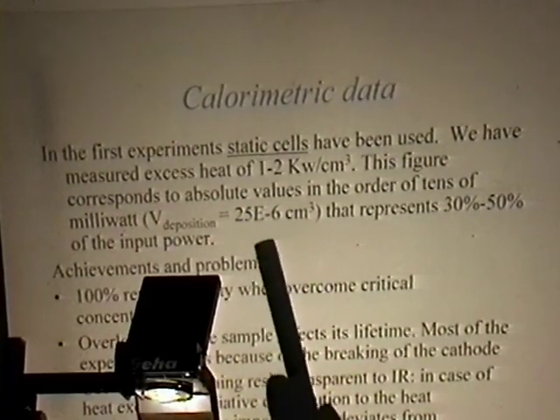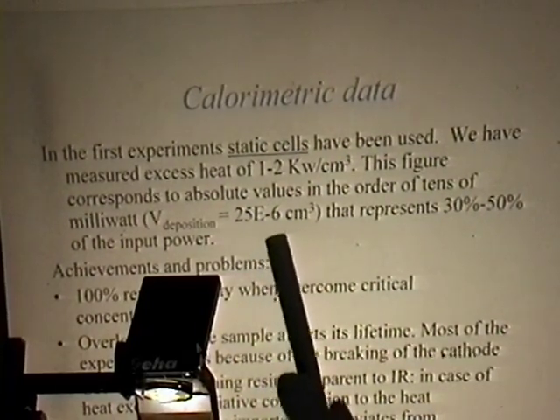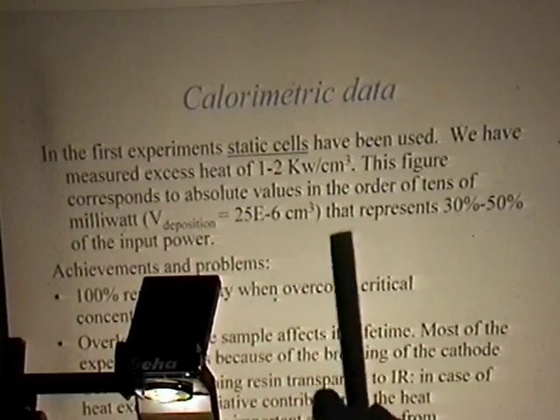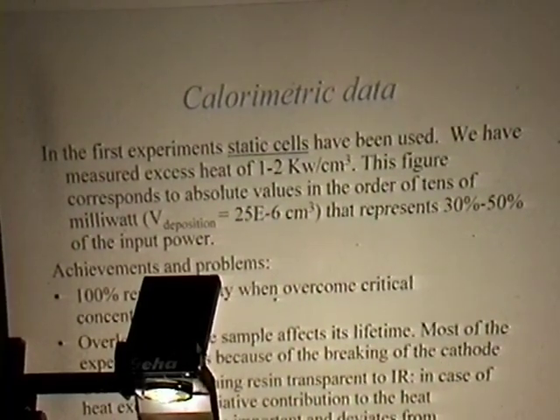The volume of the deposition is 25 × 10⁻⁶ cubic centimeters. So the net heat excess is in the order of 30-50 milliwatts. That corresponds sometimes to 50% of the input power. Usually the experiment stops because the deposition breaks.